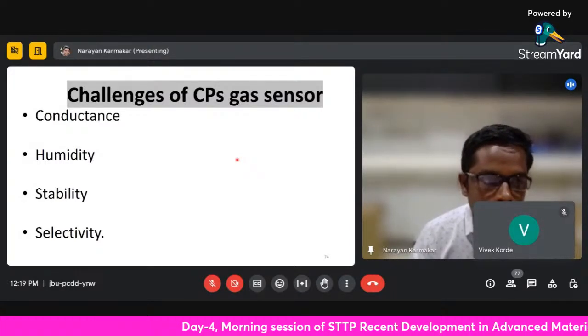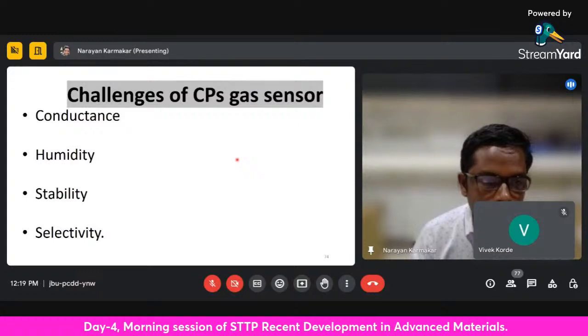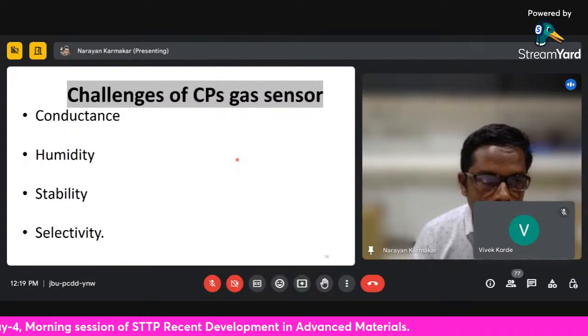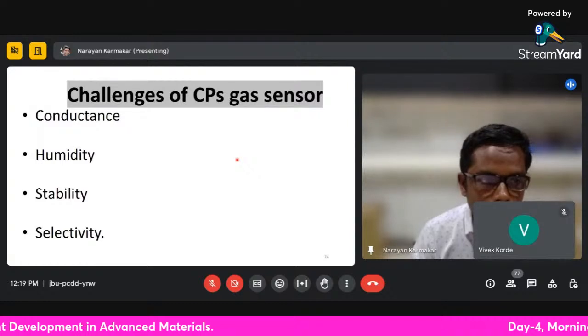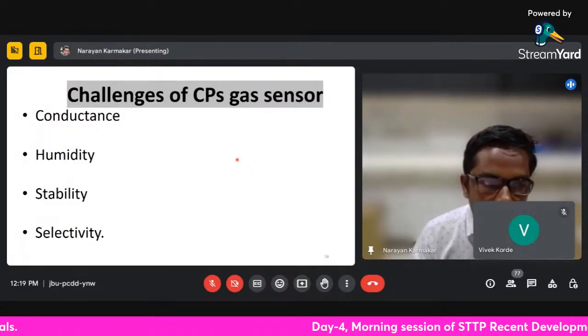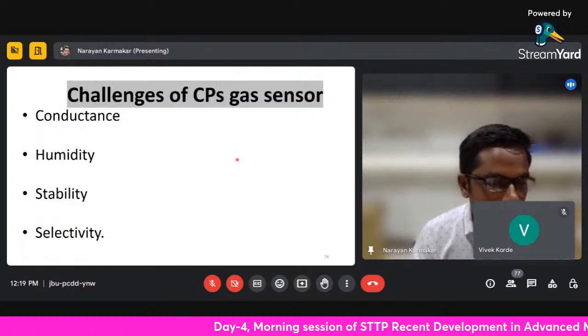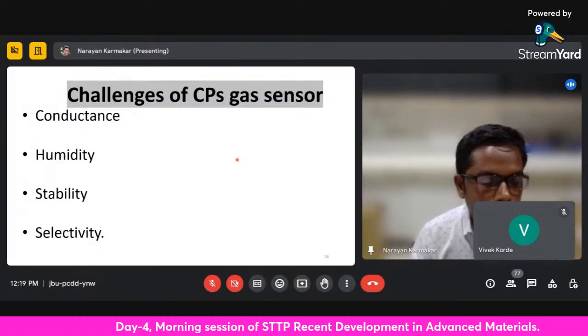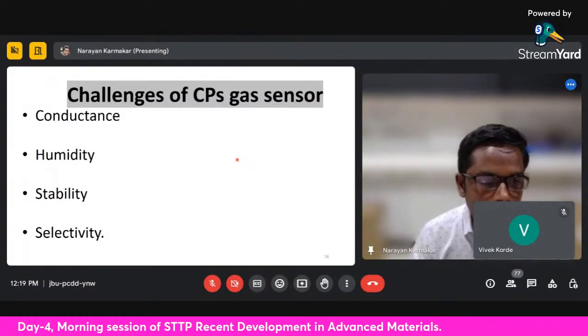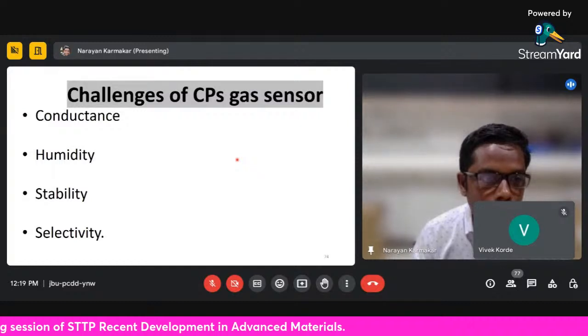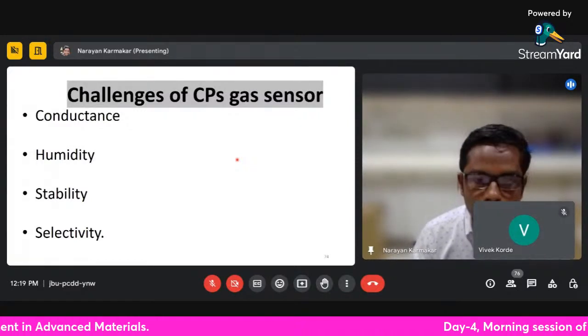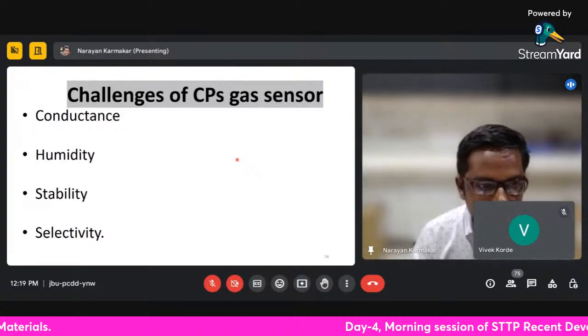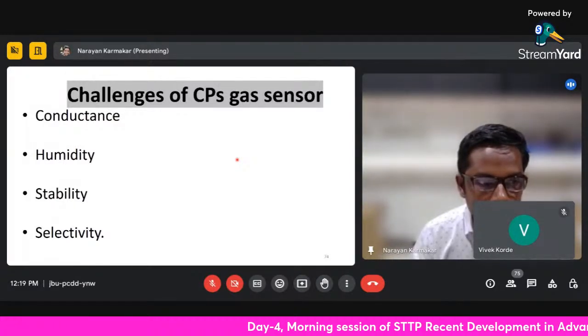So the main challenge is that we design a composite, or fabricate a conducting polymer, whose conductivity does not change with a small variation in temperature. And also the main problem is humidity. Humidity is a very crucial factor over here. So we need to make use of a different enclosure to improve the humidity tolerance of this gas sensor.